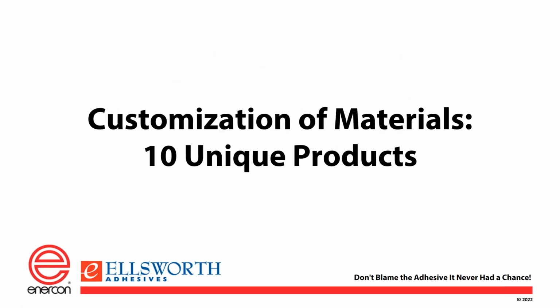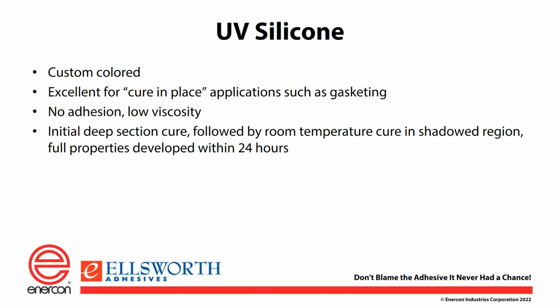10 unique products. I hope it's 10. In any case, UV silicone, kind of unique product. It was a gasketing type of application, I believe. It needed to be dispensed onto a plastic substrate, and exposed locations would be hit with UV light to immobilize it so that the device could be moved down the production line. Condensation cure continues in dark sections, and within 24 hours, there's a complete cure. A little unusual product, but a very good one. It's also a pretty color. I think that's an important thing to note.